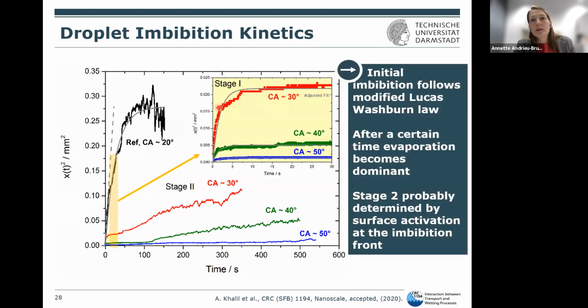And if you then zoom in, you can fit this with a model that was adapted from the Lucas-Washburn law. What you can conclude from this is that at the initial stage, basically you have a kind of Lucas-Washburn imbibition, but then the second part cannot be explained by this, because after a certain time, evaporation becomes dominant. And as you have these nanoscale pores, what actually happens, and this is the explanation for the oscillation of the fluid front, is that you have constant evaporation and condensation just at the point of the fluid front. And this then leads to this oscillation.